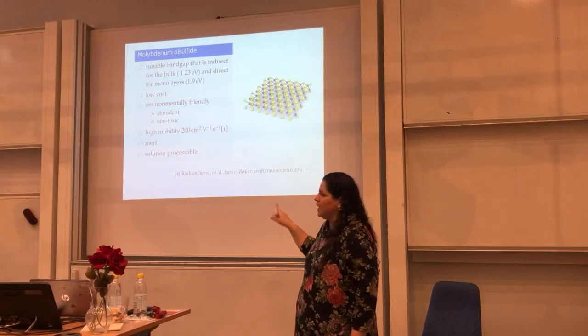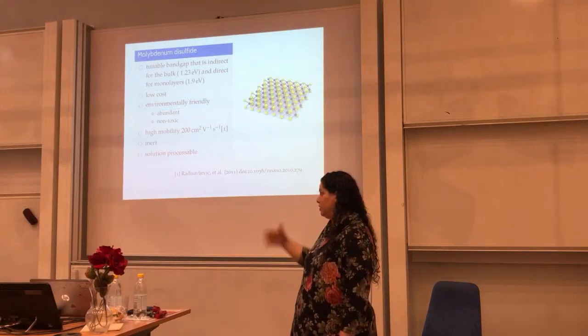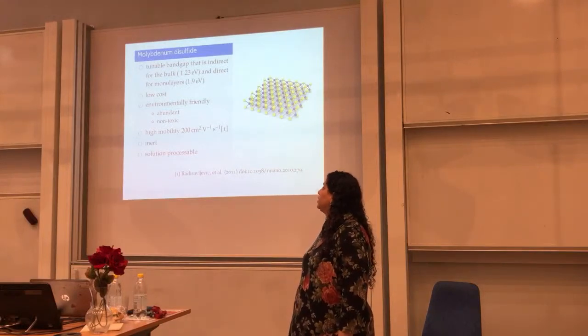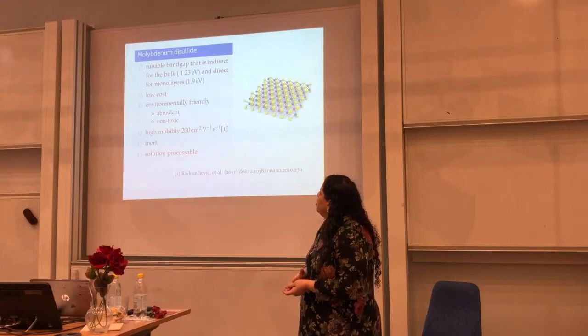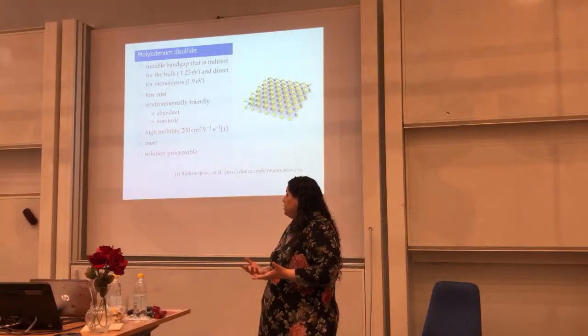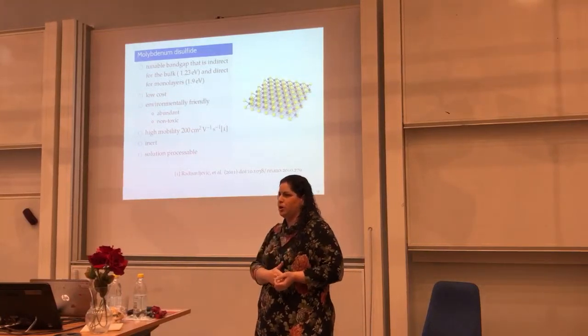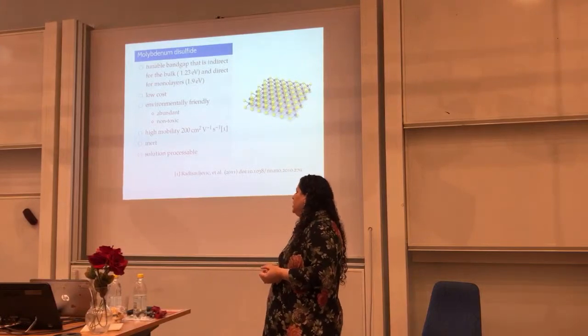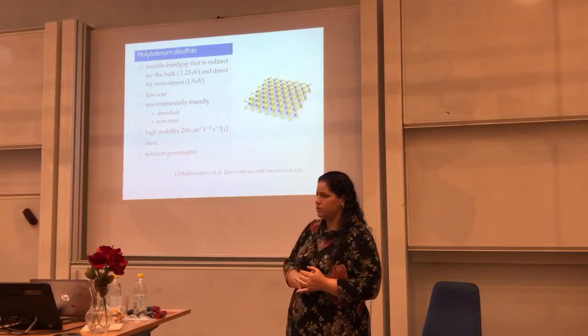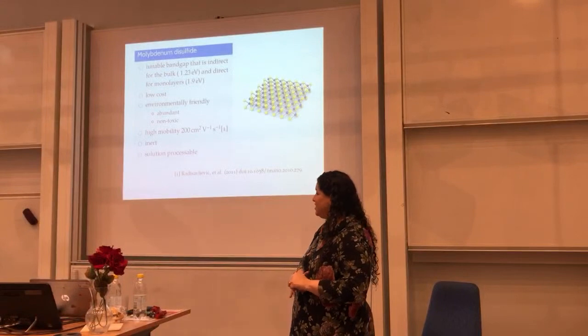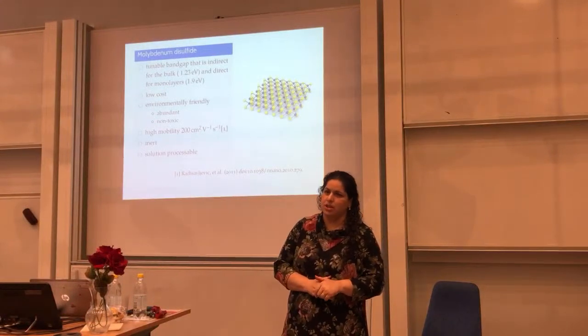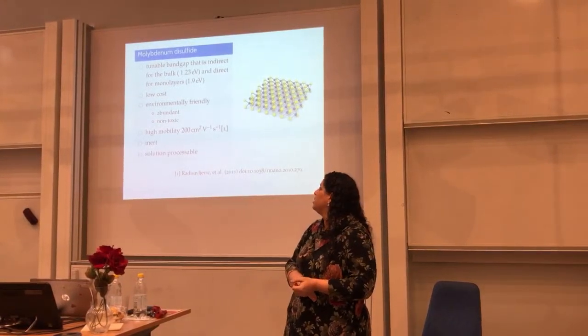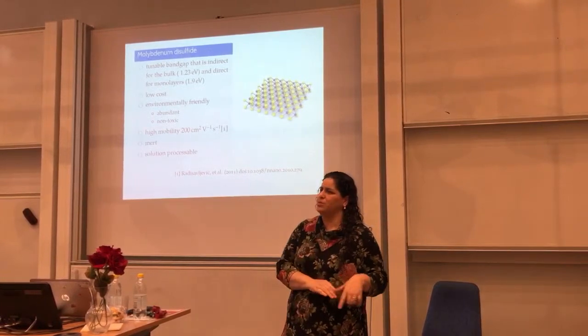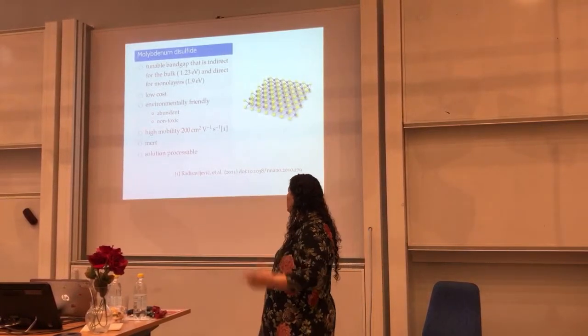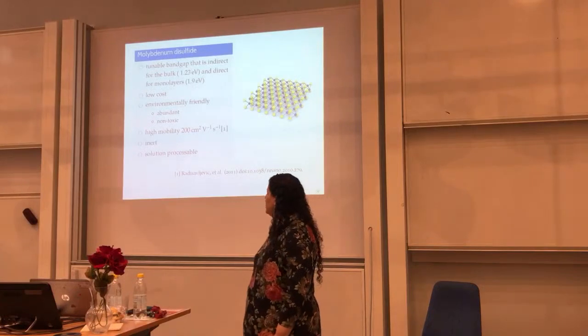And already in a bilayer, the band gap is indirect again. Besides, molybdenum sulfide is an abundant material, and it's very low cost, and that's why it's also very, very interesting to work with these materials. They need to be low cost to be able to reach the market, because the cost of production is a bit high because of the low concentration you get. I will talk about that.